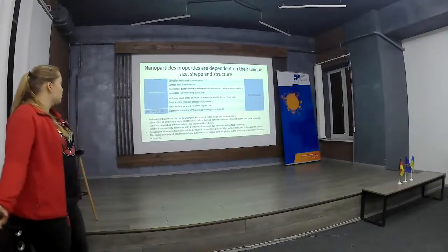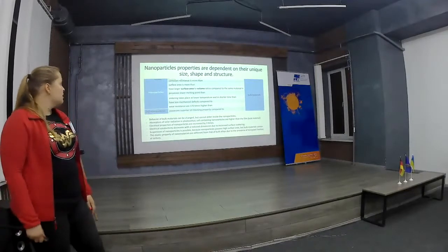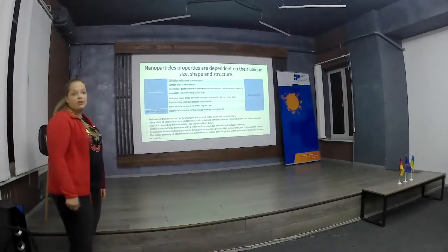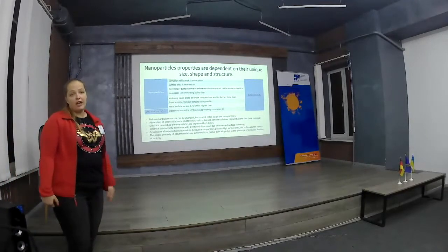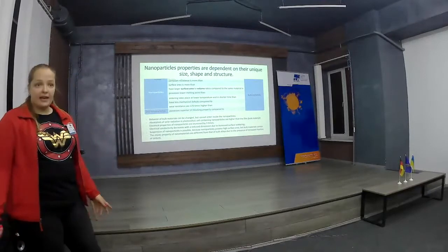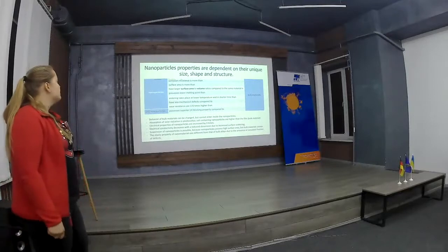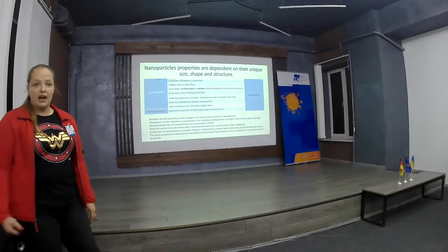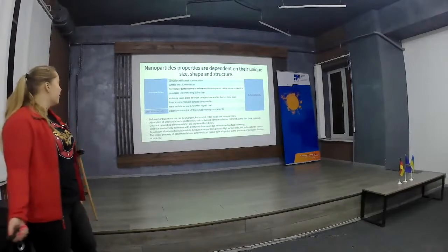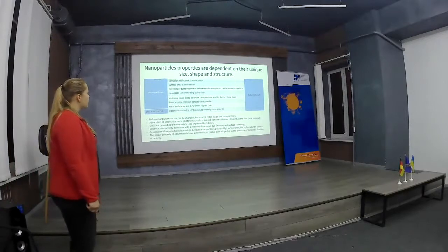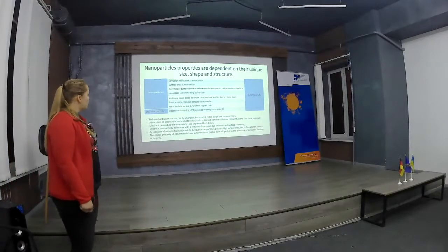Because of their properties, they possess a lower melting point, and sintering takes place at lower temperature and in shorter time than for bulk material. They have fewer mechanical defects, and their wear resistance is 170 times higher than for bulk material. Of course, they have some unique optical properties.